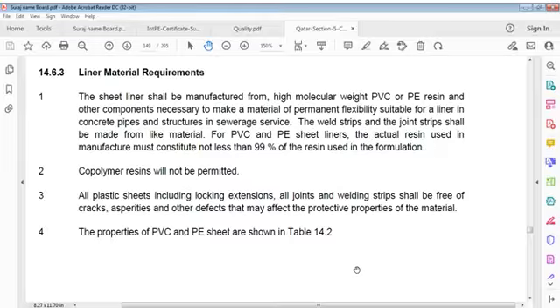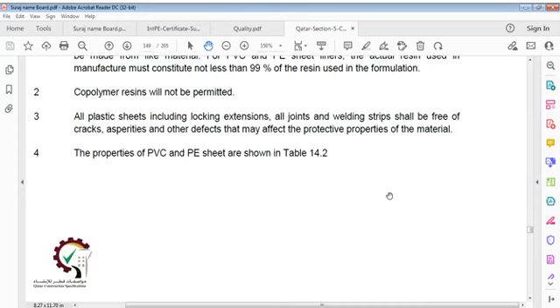Sheet liner shall be manufactured from high molecular weight PVC or PE resin and other components necessary to make a material of permanent flexibility suitable for a liner in concrete pipes and structures in sewerage service. Weld strips and joint strips shall be made from like material PVC and PE sheet liners. Actual resin used in manufacture must constitute not less than 99% resin used in formulation. Copolymer resin will not be permitted.